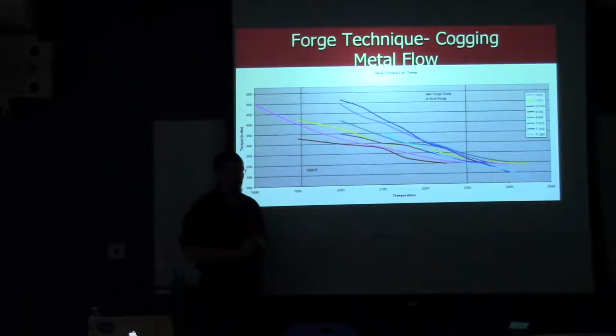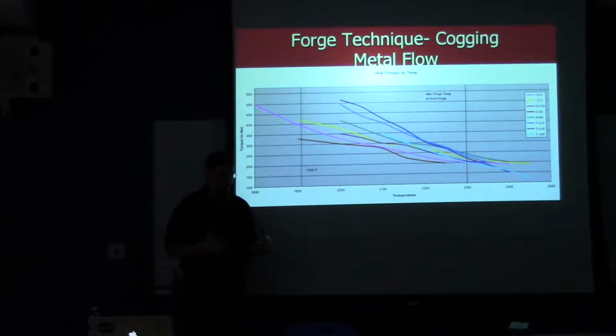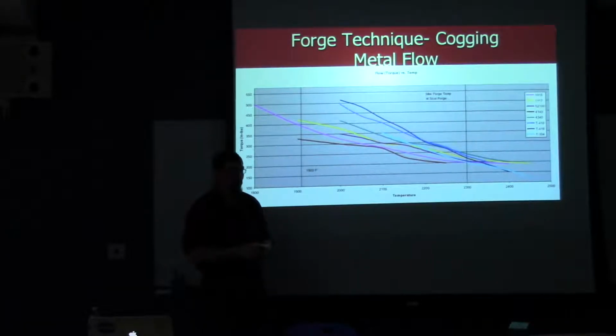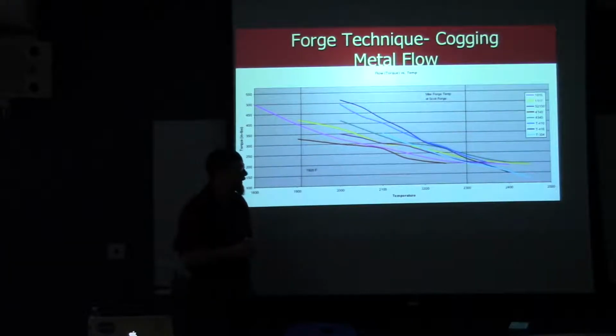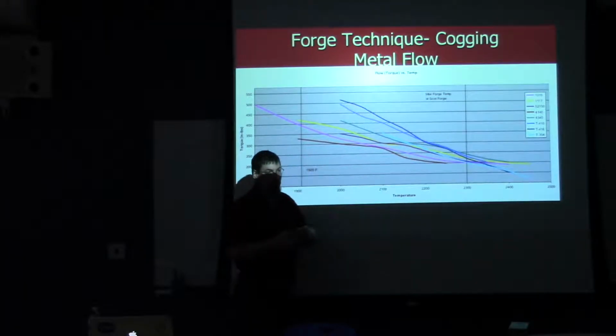So the grain boundary melting is probably one of the most important, based on local chemical segregation. But related to it is that when we start doing deformation, your deformation is going to cause friction. We've been talking about that for the last 2 weeks. What happens when you have friction? If I rub my hands together, they're going to get warmer, right? The same thing happens even if my metal's at 2300 degrees. If I start smashing those atoms together, making them move back and forth against one another, they're going to get hotter. You may see this in your forging lab. If you're forging away on something, you can actually cause the metal to increase in temperature if you're fast enough with it, right? So we have to allow for that in the forging process, so you have to have some extra cushion because you're going to get internal heating. It's called adiabatic heating from internal friction. So those are the two primary reasons.